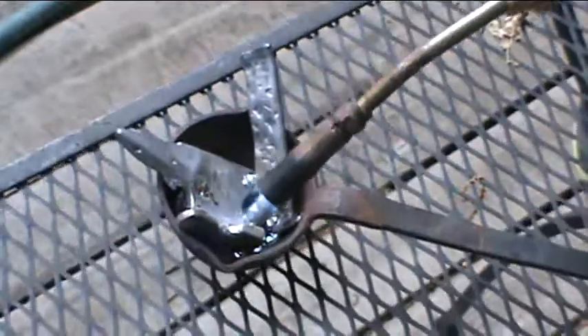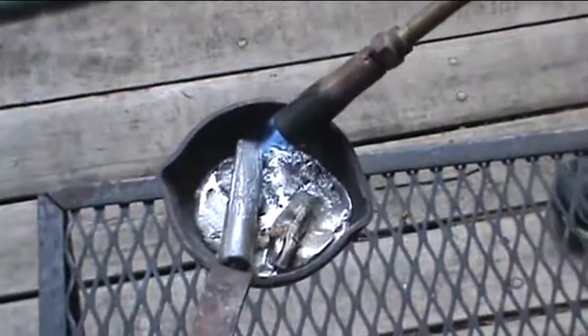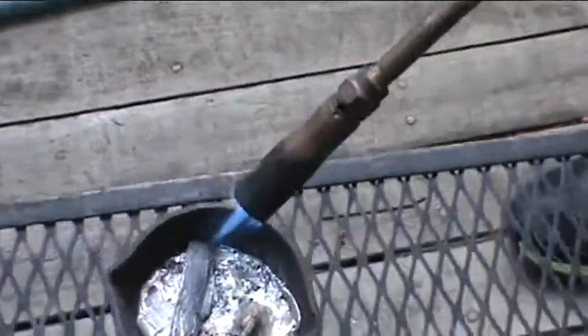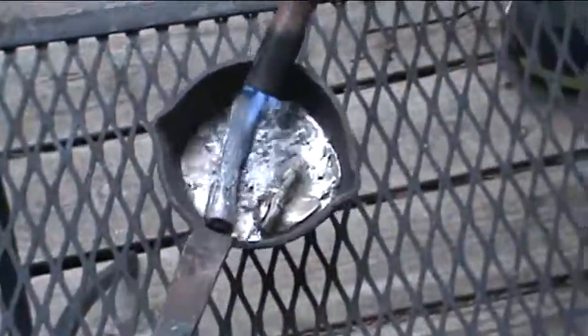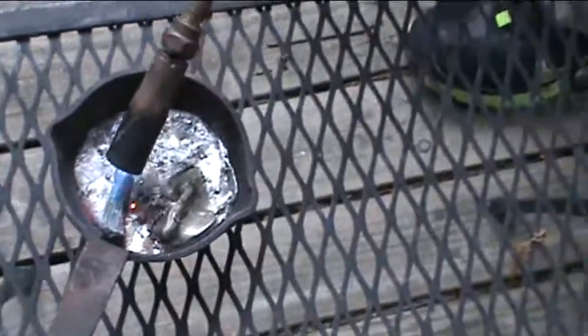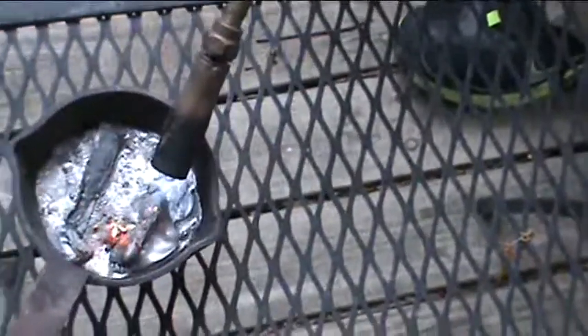You can see we're using one of our rejected castings as stock. When you have molten tin or any molten metal, you don't want to add any kind of wet or dirty metal to the charge. You want to always use clean, dry metal. We want to make sure we get this fully liquid before we begin to pour it.